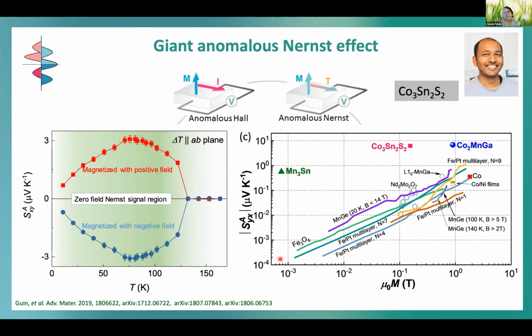If you compare the Nernst effect versus magnetization, it was believed for a long time that this goes linear with magnetization. This is the case for many materials, but these topological materials—I can't talk about all of them—show this unusual behavior.